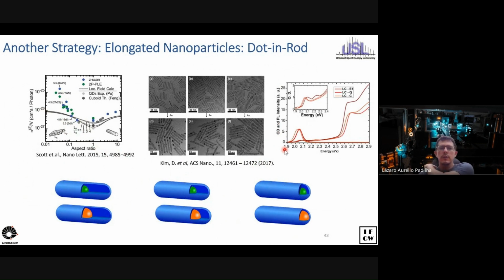Another step forward on this is to look into structures that are not spherical. That's the case for the dot-in-rod nanoparticles, in which the shell is rod shaped. And if you remember the beginning of this talk, I mentioned that people have shown enhancement of two-photon absorption by changing the shape. So here we want to look at how the shape and also the position of the core interferes with the two-photon absorption cross-section.